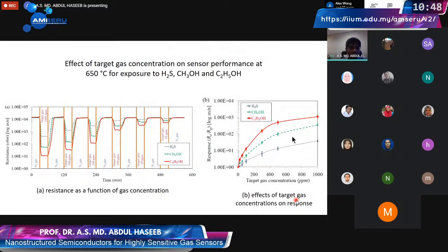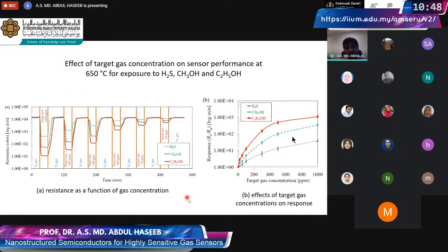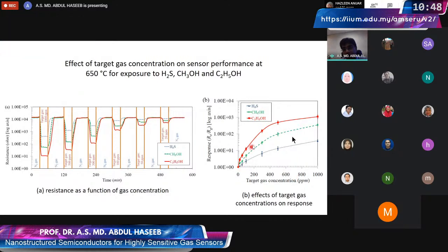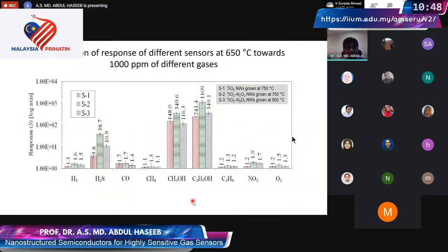We can also look at the sensors at different concentration and different time, and we see that even at 20 ppm concentration, we can get some decent signal, which can be useful for detecting these gases. And the response of the sensor towards different gases changes with gas concentration. Initially, the response changes quite rapidly, and then it levels off, which is usually a normal behavior that we see in other cases as well.